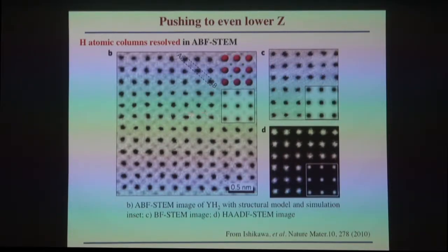And so the idea that you could have random hydrogen atoms in different places, I just don't think it's going to be possible. The energy that's needed to displace them is much, much less than you're going to get with the electrons in the electron microscope. So even if you went down to 10 kV or even lower, it might be impossible to avoid the likelihood that the hydrogen atoms will get displaced. So I'm not going to say that in my lifetime or any of your lifetimes you're going to see hydrogen atoms segregated to grain boundaries in many of these interesting materials. Okay. Sorry to be a pessimist, Paul.